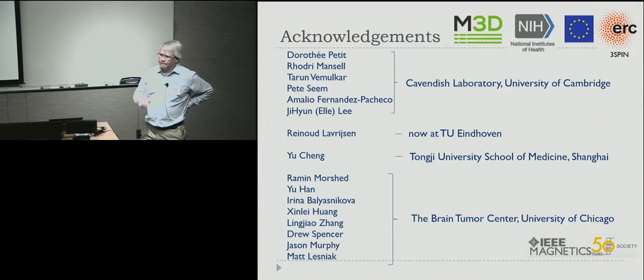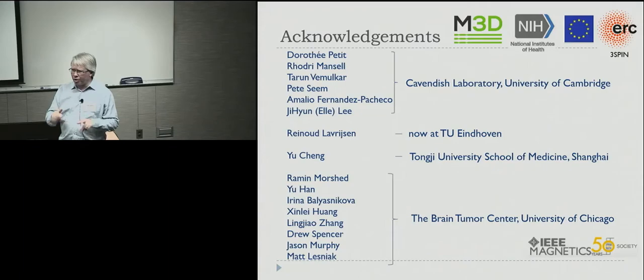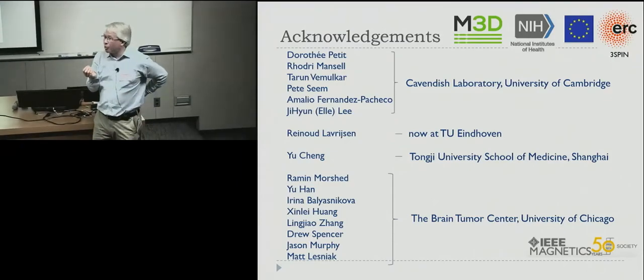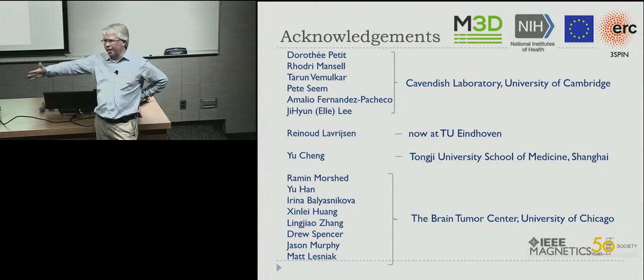As long as you have a multi-domain, that could be okay, right? Well, it's a single domain at remanence. I think it's important to distinguish multi-domain at remanence from a system that uses a domain wall as a switching mechanism. But I think we know from MRAM that surprisingly small things, maybe 100 nanometers in a perpendicular system, because the wall is so narrow, still involve a domain wall for switching.